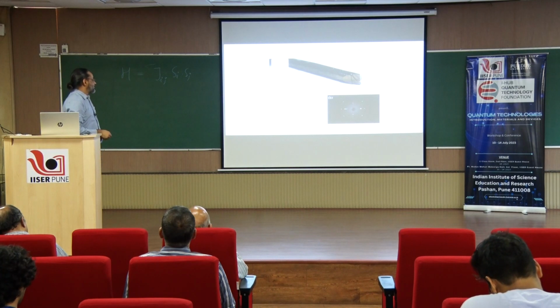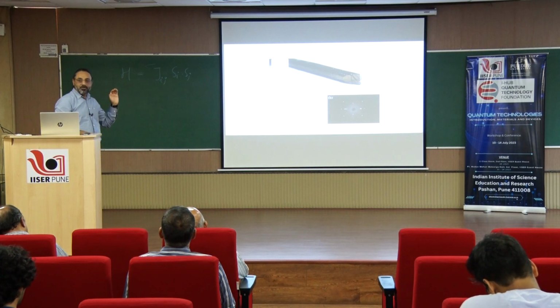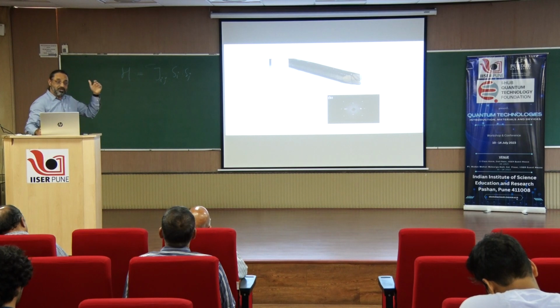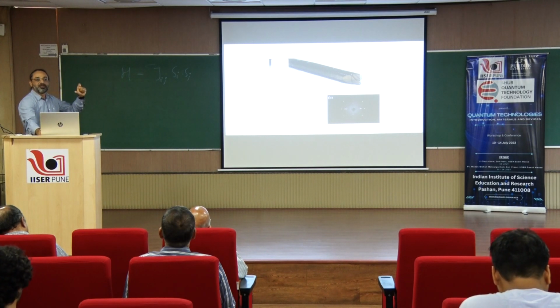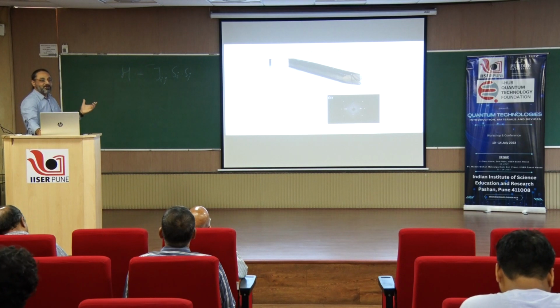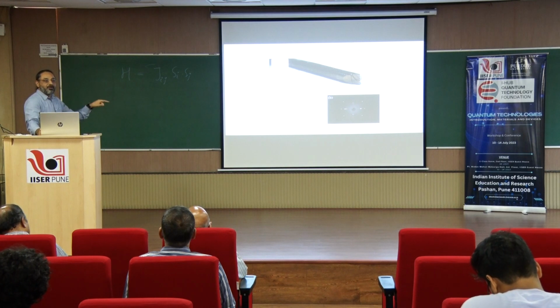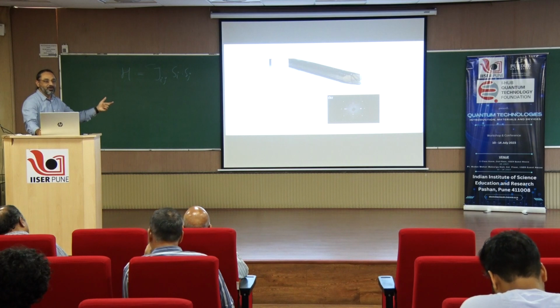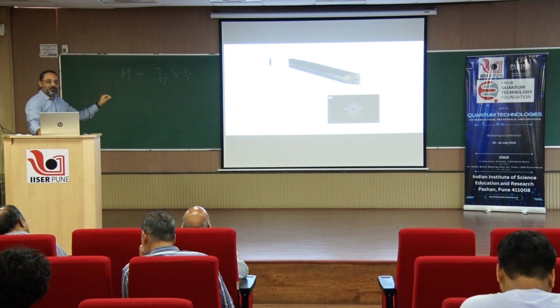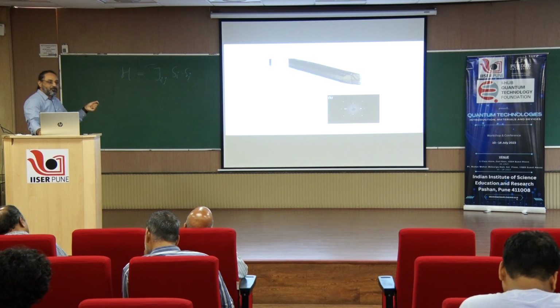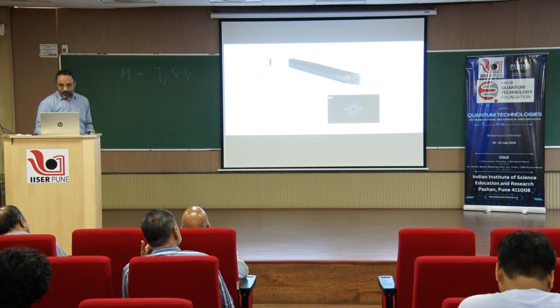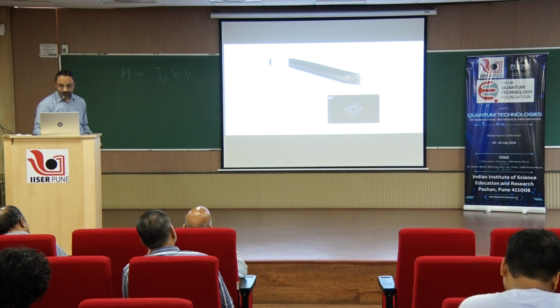So basically this analysis tells you about the quality of your material in much greater detail than any other technique. For instance, if you use X-rays, they cannot penetrate into the bulk of the material, but the neutrons can. Why? Because they are electrically neutral. They only have a spin, so they interact only with the spin degrees of freedom. And if your material is not magnetically ordered, then of course it doesn't matter that much. All right. So this is an example of how the materials are characterized.